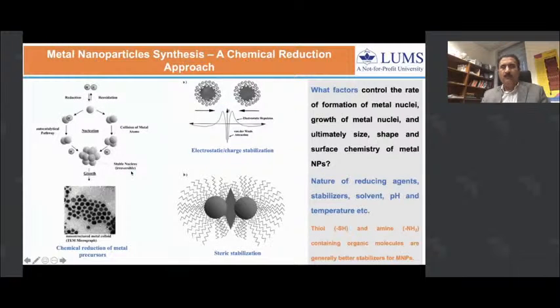This is how we prepare these metal nanoparticles. There are a variety of methods you can use, but the method we use is very simple, based on a chemical reduction approach. We start from metal precursors and then reduce them using a certain reducing agent in the presence of a certain stabilizer. The metal ion, for example, is reduced to a metal atom, which will attract other reduced metal atoms or ions to form metal nuclei at the initial stage, and these nuclei grow further into bigger metal nanoparticles.